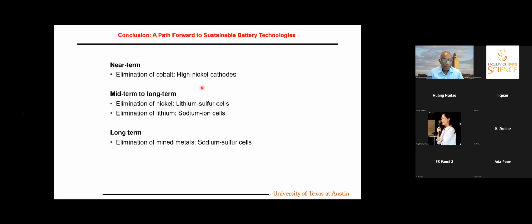And then elimination of lithium, sodium ion cells. Lot of things are happening again. Possible long term, the elimination of mined metals, maybe sodium sulfur cells. It may take much longer than lithium sulfur because not too much work is done. You already saw at least in one of them, the electrolyte makes a big difference compared to the conventional electrolyte versus the localized high concentration electrolyte with sodium sulfur cells.